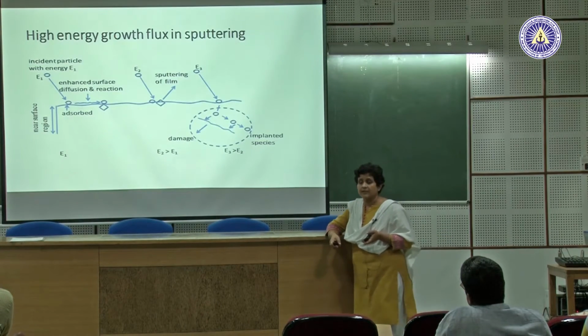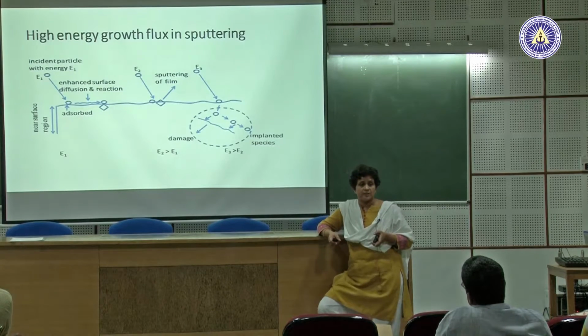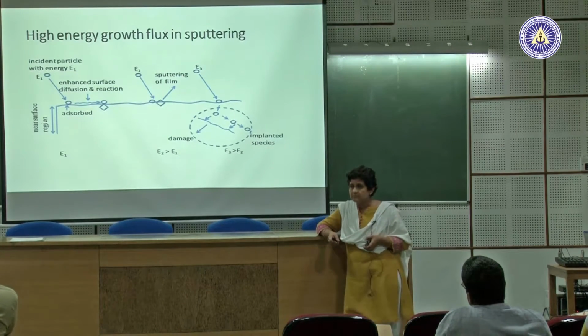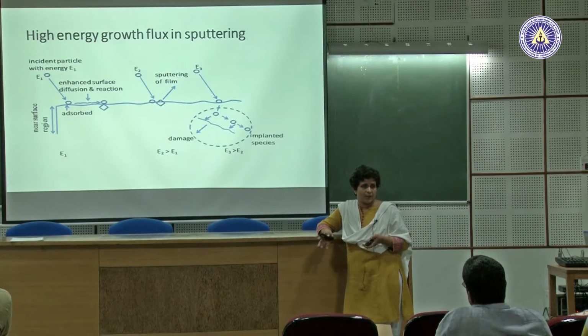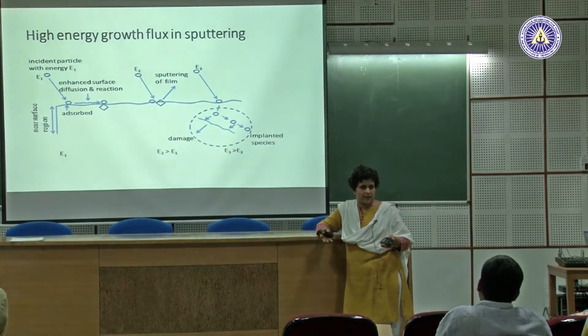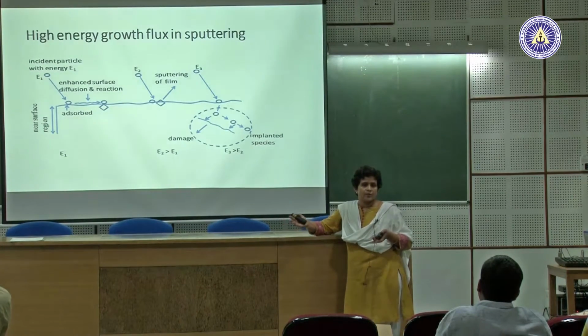And this you must have seen, I am sure you must have used these processes, plasma cleaning, right? Plasma cleaning is basically a subset of what I am talking about. What do you do in plasma cleaning? You create an inert gas plasma and you hit the substrate by putting it at a cathode. So whatever loosely attached things are there, they will just get sputtered out. You will clean the surface, right? So that can happen on the cathode, it can also happen on the anode. So if your energy ranges are not right, rather than depositing a film, you will be sputtering it off.